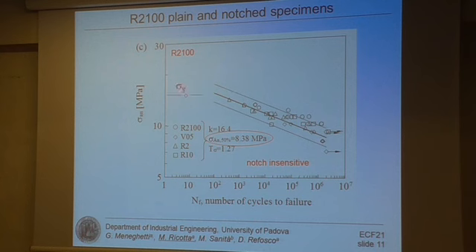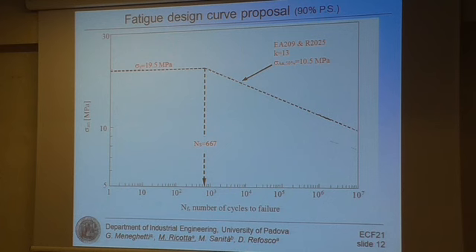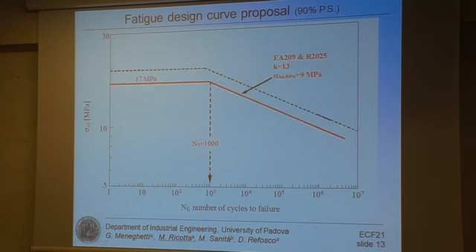The low cycle fatigue zone is characterized by a fatigue strength that is practically equal to the yield strength of the material. Therefore, we propose two different fatigue design curves. Here, I will show you the fatigue curves at 50% survival probability that I showed you before for both these compounds. And then we have calculated the fatigue curve at 90% survival probability, having a fatigue strength calculated at 2 million cycles equal to 9 megapascal, and we have cut the low cycle fatigue zone with the fatigue strength evaluated at 1000 cycles.